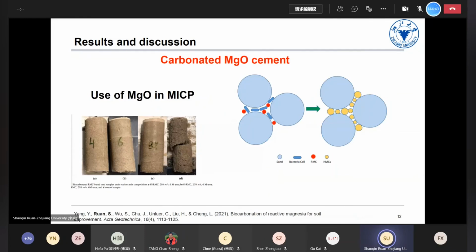And previous speakers also mentioned MICP. MICP is also a quite popular research direction in this area. It uses bacteria and some calcium-bearing salts, like calcium chloride. Actually, previously, we also conducted some research regarding the use of MgO in MICP. We introduced the reactive magnesium cement and the bacteria, and it will produce hydrated magnesium carbonates to solidify these sands. The results are quite good, and I think it is a very promising field.